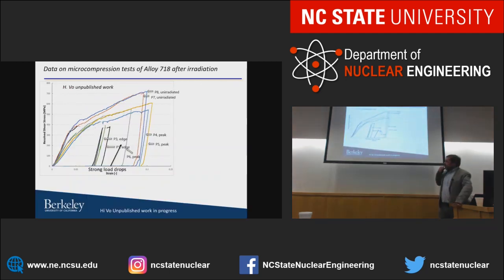So if you look at our stress strain curves, we would expect from this that our unirradiated material is the strongest because it has the most precipitates. And so indeed, the unirradiated material is actually the strongest. As you irradiate it, your precipitates go away, and so it becomes weaker. Now, interestingly, the lower dose material, which is the edge, shows us these jumps here, very distinct jumps. They form so fast, again, this example from earlier that we punch our neighbor, versus the peak region actually doesn't have these jumps continuously.